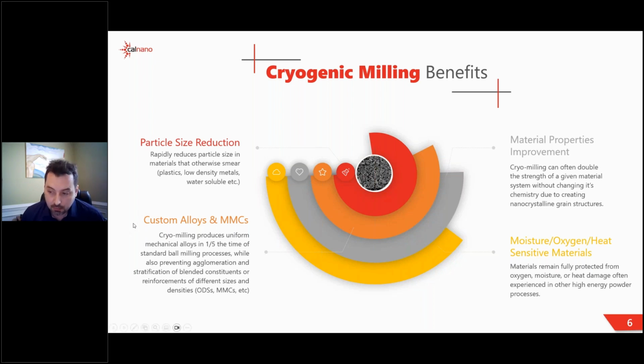The area that we probably see the most applications in is a different version. In that example, I was not changing the chemistry of the material, we were just changing the microstructure. But another capability of cryomilling is the ability to change chemistries in addition to the microstructures, where we can create custom alloys. As an example, we have one customer where we develop 5 new variant alloys every week at different scales, where they have a large design of experiment with different alloy compositions they'd like to evaluate for their very specific application. And starting from powdered materials and raw constituents, we can just create whatever alloy composition you want very rapidly.